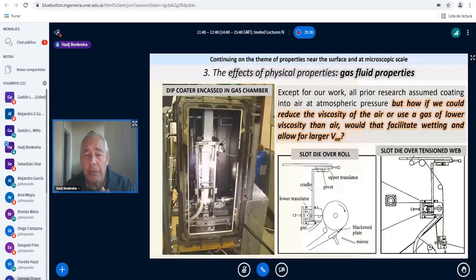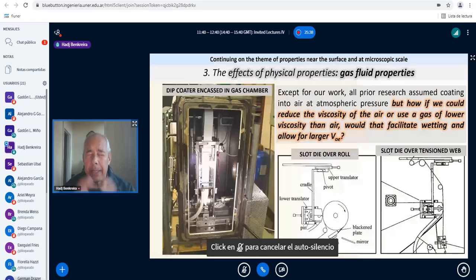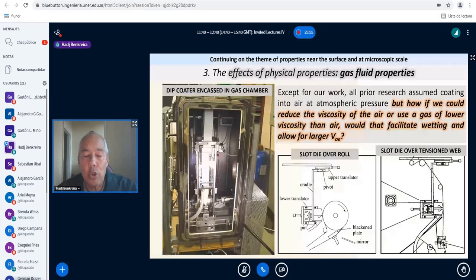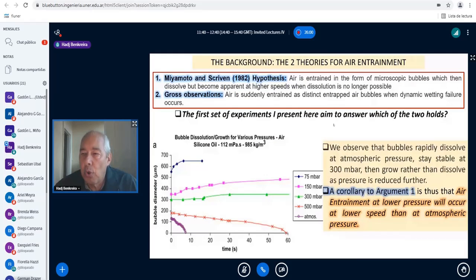The first thing then, before we look at the data, at the time, before we did our experiment, there were two theories for air entrainment. There was one which is attributed to Scriven and his student Miyamoto. And the idea, according to Scriven, was that air is always entrained. It's just that we do not see it. It is absorbed, it is dissolved. It's only when it can no longer be dissolved that you have air entrainment. And this is the hypothesis of Scriven.